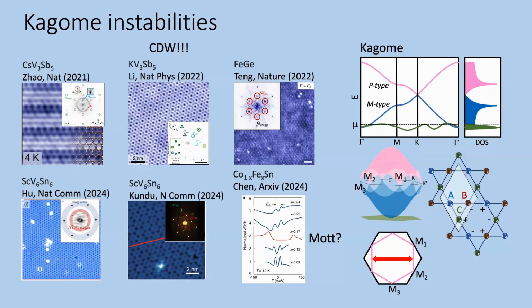But we would like to talk today about the flat band physics, and there's one interesting work I would like to refer to from Bertold Jäck that grew thin films of cobalt tin, which is another kagome material, and gated them, with doping of iron, towards the Fermi level, towards the flat band, and at some doping, he sees a spectrum like the one plotted in red, which starts to resemble a Mott insulator. So presumably the flat band, once slightly doped, just splits into an upper and lower Hubbard band, and this is how the interaction energy is lowered.